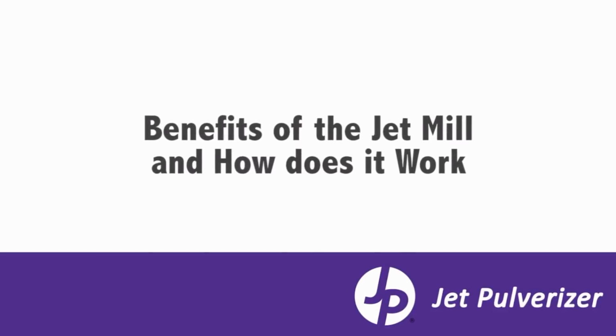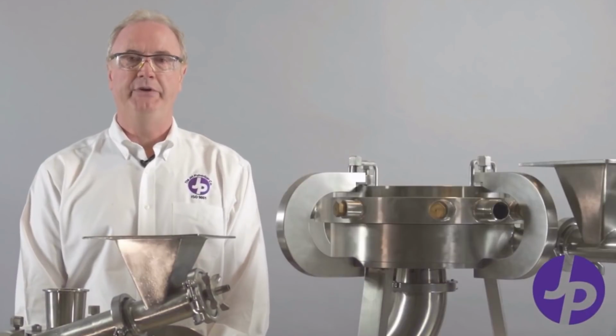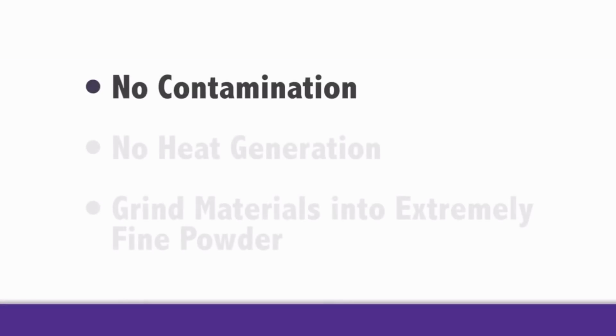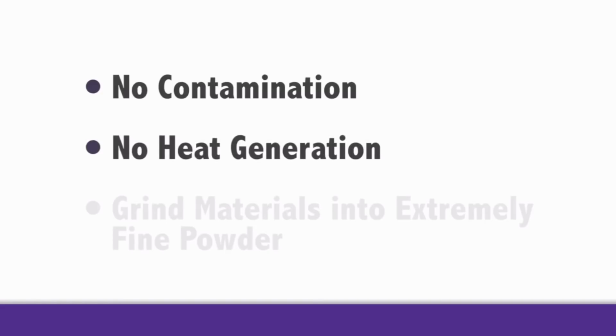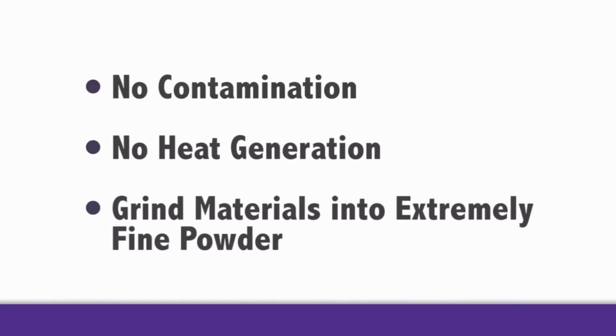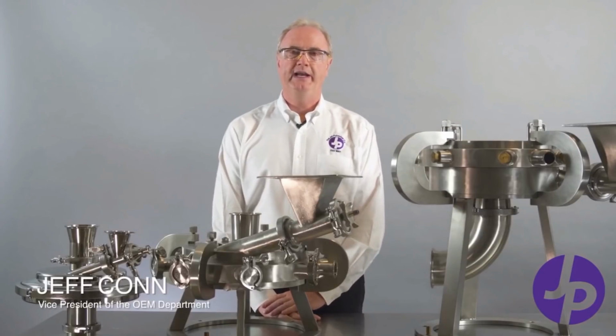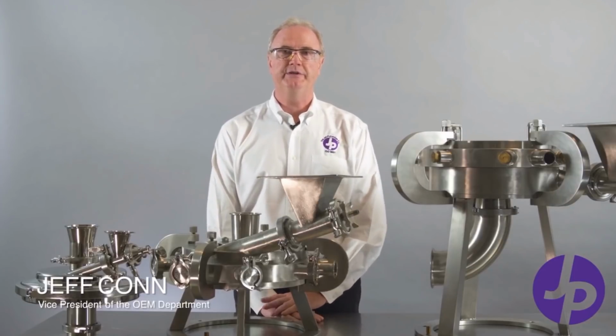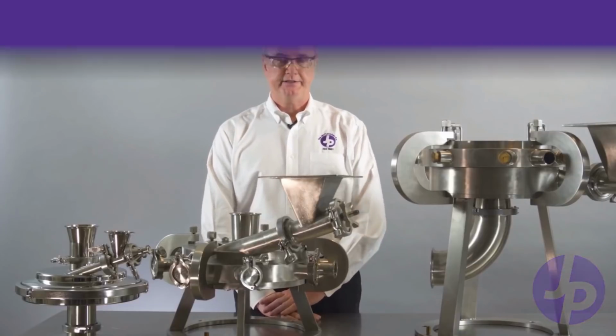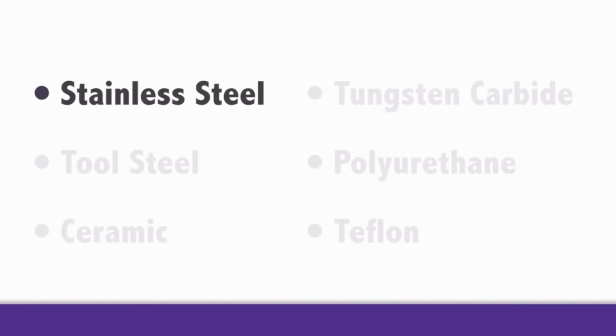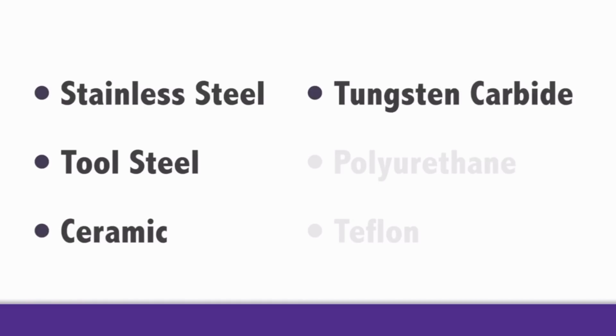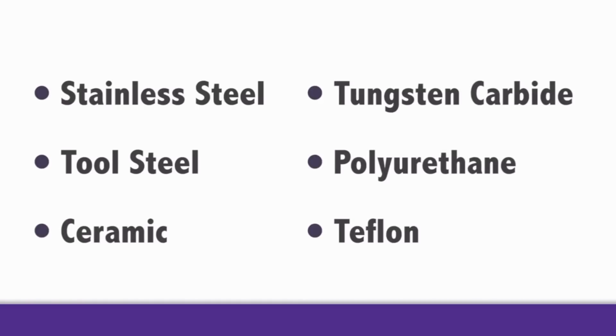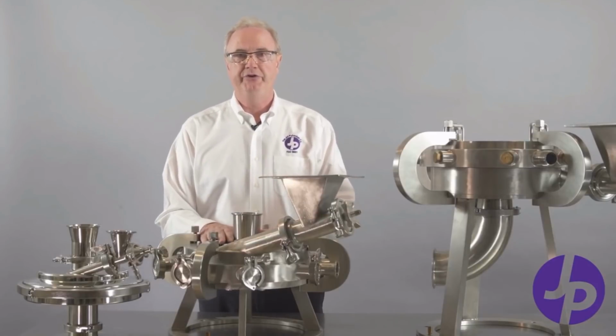The benefits of the jet mill are many. We're able to grind materials without any contamination. We're able to grind materials without any heat generation. And we're able to grind materials extremely fine, finer than any other dry method available. Jet mills will grind friable or brittle materials or crystalline materials to the 1/3 to 15 micron particle size range. We manufacture jet mills in 11 different sizes. The internal components can be stainless steel, they can be tool steel, they can be of ceramic, tungsten carbide, polyurethane, Teflon. Jet mills are also known as fluid energy mills.